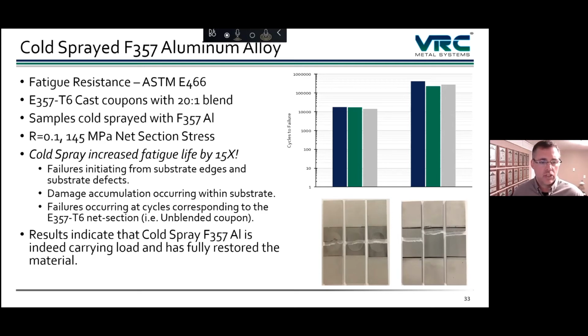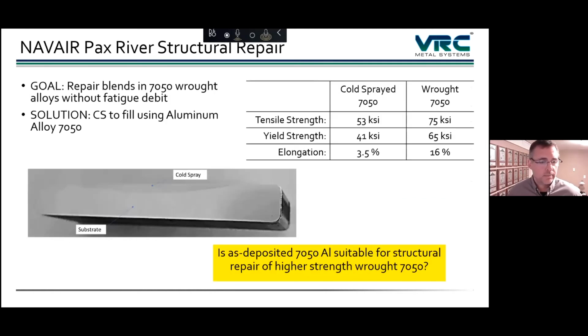In this case, you're seeing an order of magnitude increase, and we've shifted the failure to a fairly random location with the samples on the right, as compared to all of the samples failing right in the middle of the divot on the left. So we've actually brought the samples back to a pristine condition in this particular case.